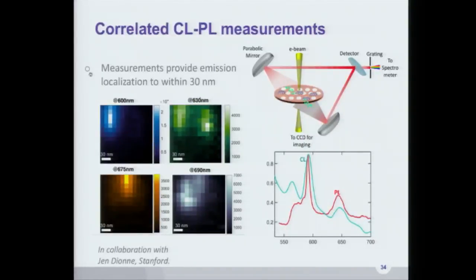And they're not the only ones to measure things that sound like something beyond just a point defect is happening. Everyone keeps saying they see the best emitters in the crappiest samples that they have, which is always a little bit suspicious to me. And I think it comes from the fact that some of the emitters that are actually being measured are the rarer and not so easy to form ones, rather than the more native point defects.